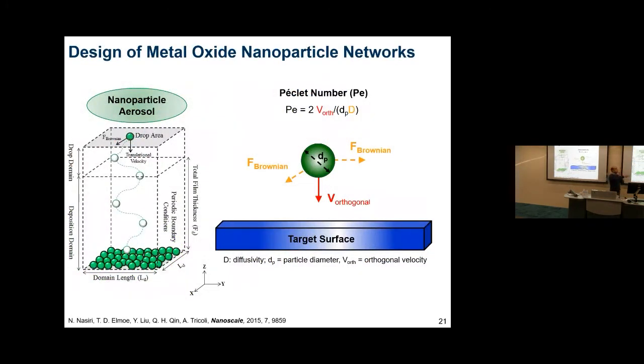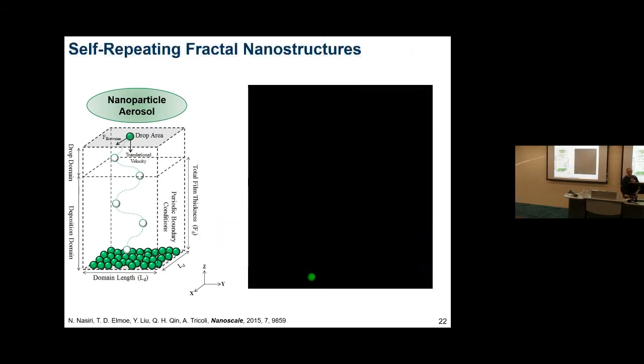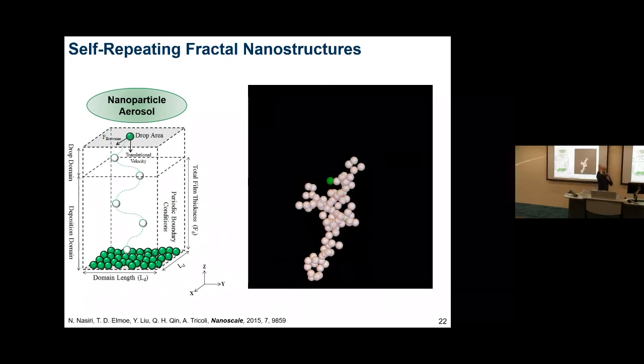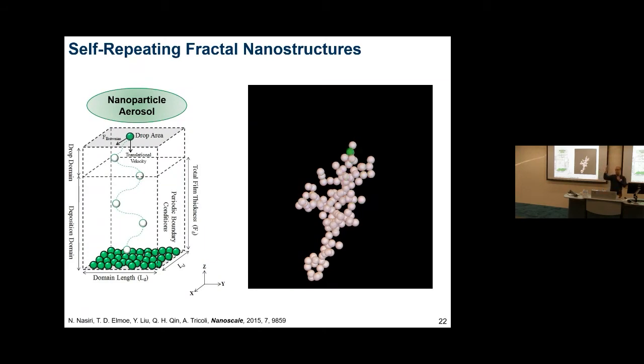So you create an aerosol with a nanoparticle, semiconductor, gold, whatever you like. Then if you control the diffusion and the settling, this is the Peclet number, you can exactly control the porosity. This is a simulation, particle dynamic simulation, of what happens in the diffusion regime. So you're almost always in the diffusion regime with nanoparticles, and you create this beautiful fractal-like structure that self-repeats over surfaces.